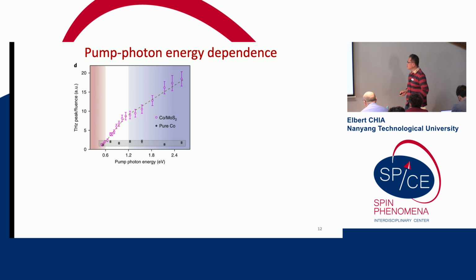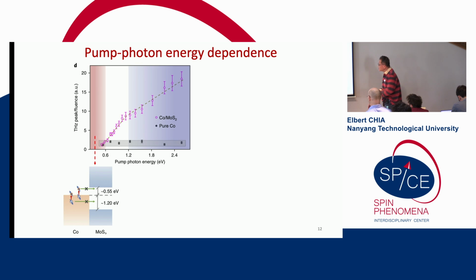And the slope is actually a smaller slope. So we asked Marco, and Marco said it's easy to explain. So first, when we pump at less than 0.55 or 0.6 eV, both the spin up, the majority and minority spins, do not have enough energy to overcome the Schottky barrier, whether it's an electron or hole Schottky barrier. So all the Terahertz emission that we got is just from pure cobalt.